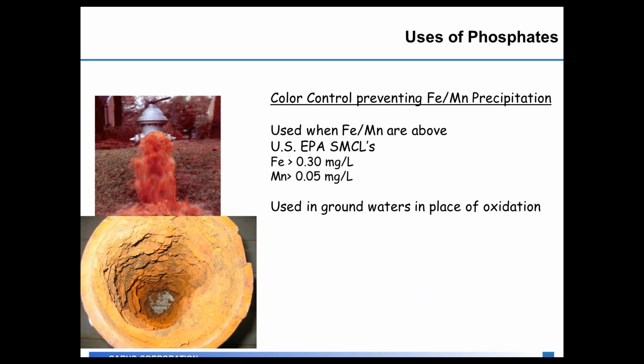For color control, preventing the iron and manganese from precipitating out, these are typically used when the iron and manganese are above the US EPA SMCLs. An SMCL is a secondary maximum contaminant level, which states that there's no health effects from drinking iron and manganese above these levels, but it's going to cause discoloration of the water and staining of laundry and fixtures in the consumer's home, which is going to lead to customer complaints. The SMCL for iron is 0.3 milligrams per liter, and for manganese is 0.05 milligrams per liter.